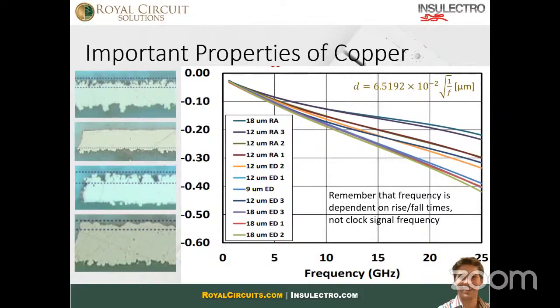And that tells us what we should expect from an insertion loss standpoint, because as the signal starts to increase in speed and in frequency, the surface roughness of the conductor starts becoming the predominant loss factor in your electricals. So the RA foils, not only do they buy us better mechanical attributes, they also buy us better electrical attributes as well.